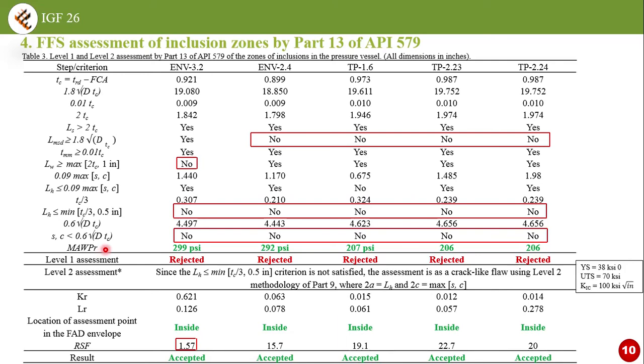And furthermore, LW has a direct effect on the remaining life of these inclusion zones. This inclusion zone has a lower remaining strength factor because the LW, or the distance between this area and the weld metal, is so close. However, the level 2 assessment has been accepted for all non-metallic inclusion zones.